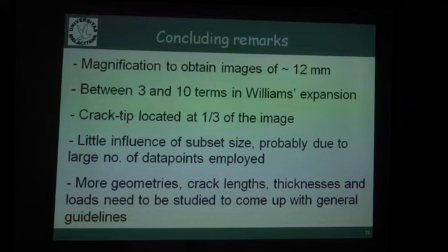The crack tip should be located at about 1/3 of the image, and we have observed very little influence of the subset size. Of course, this is a preliminary study, so we should complete it by doing a similar study with more crack lengths, more geometries, loading conditions, and so on.